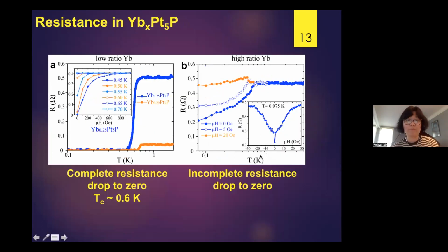However, if we measure the low ytterbium ratio, where ytterbium goes down to only 0.25, like 25% ytterbium, we see the superconducting transition very clearly at 0.6 Kelvin. So we think that's very cool.